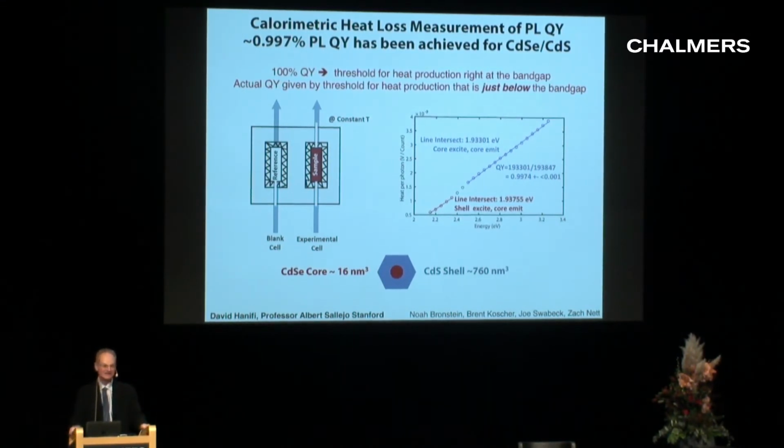It turns out that nobody knows, because if we try to measure it in a conventional way, you take your material, put it inside what's called an integrating sphere, measure how many photons come in, and try to see how much energy is put out. And you try to compare those two. That will work to about 1%. If you work really hard, maybe 0.6% or something. We need to go to many nines.